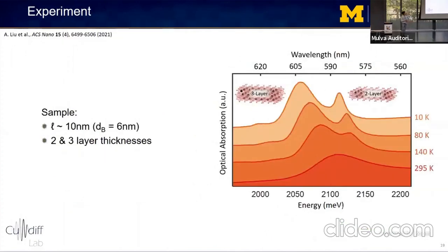So in these nanoplatelets, there are basically two dimensions we have to consider now, which are the lateral dimensions of our nanoplatelets, as well as their thicknesses. So if you look at the absorption spectra of our samples on the right, you can see two distinct exciton absorption peaks corresponding to two different nanoplatelet thicknesses.